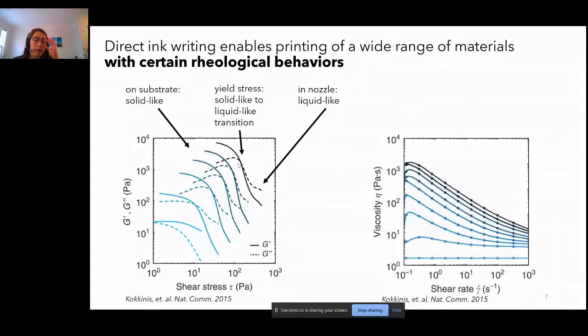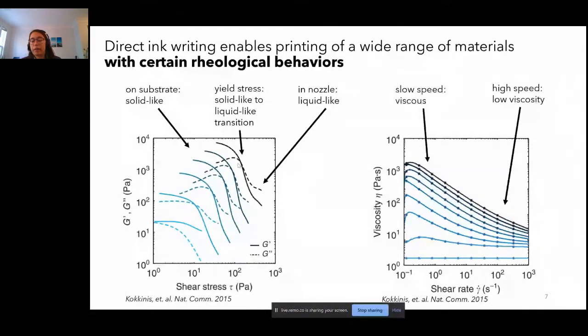Another way that you can look at the rheology of these materials is using viscosity curves. So we're looking at the viscosity as a function of shear strain rate here. And what you can see is that these are shear thinning materials. As you increase the shear rate, you decrease the viscosity. What that means is if you print at high speeds, that'll decrease the viscosity of the ink, and that means you can still get it out of the nozzle without using exceptionally high pressures. At slow speeds, such as when the ink has just come out of the nozzle, it's going to become more viscous and it'll resist flow and be able to hold its form.